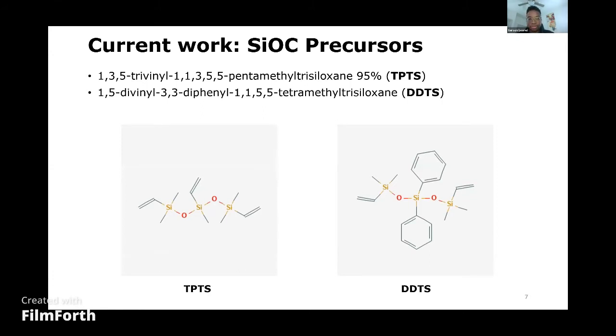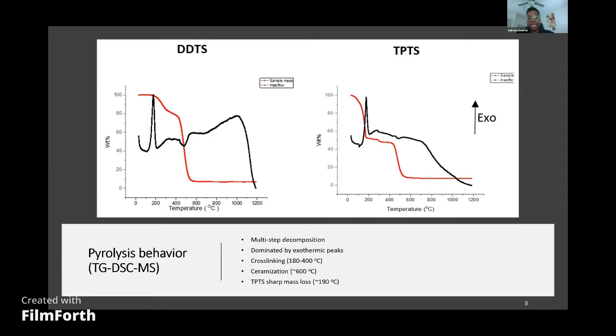To study the pyrolysis behavior of those polymeric precursors, we utilized TG-DSC coupled with a mass spectrometer. From TG-DSC, we're able to see that these materials undergo multi-step decompositions, which is expected. But what we're also able to see is that unlike in DDTS polymeric precursors, during the pyrolysis of TPTS, we see this rather sharp decrease in mass at temperatures close to around 190 degrees centigrade. So it's interesting to see this difference.